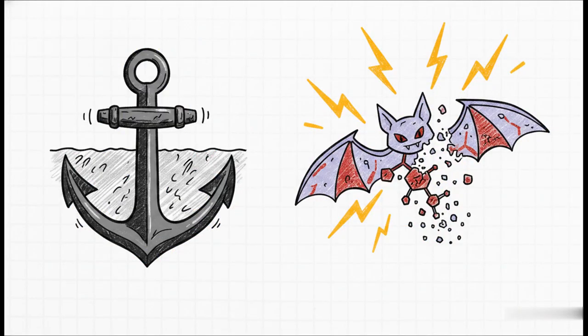Just look at these extreme capabilities. Epoxy's adhesion is simply unmatched. Up to a 15 megapascal grip on steel. It literally anchors itself into the metal's microstructure. Plus, you get practically zero volume shrinkage, so you can apply massive, thick coats in a single pass. Sounds perfect, right? But here's its fatal flaw.